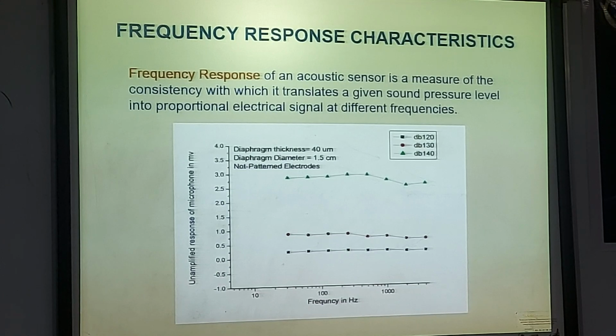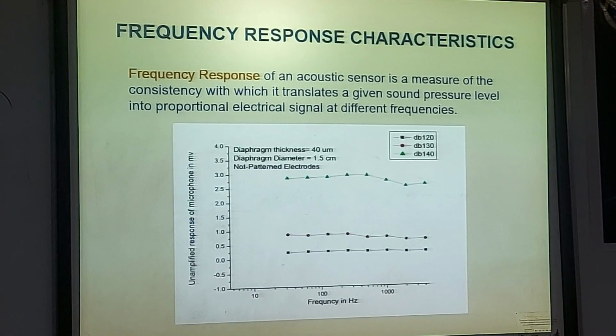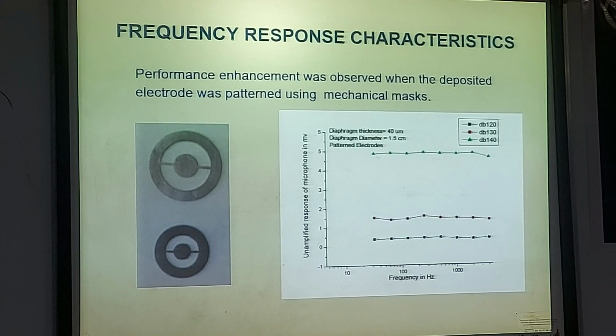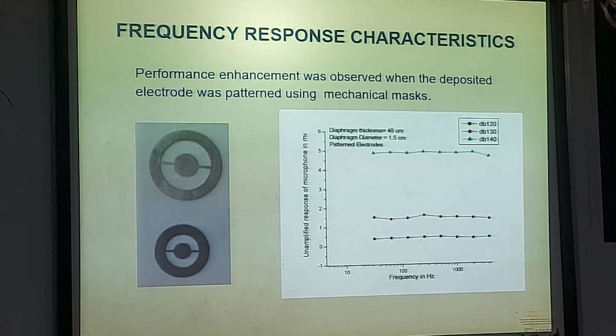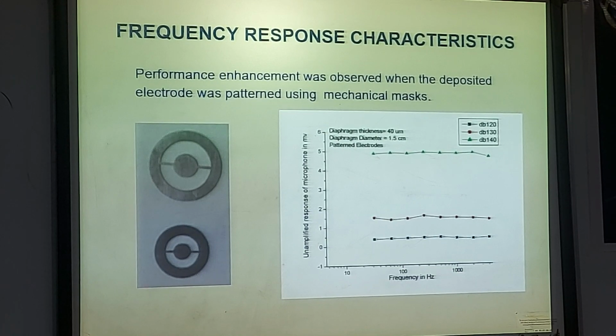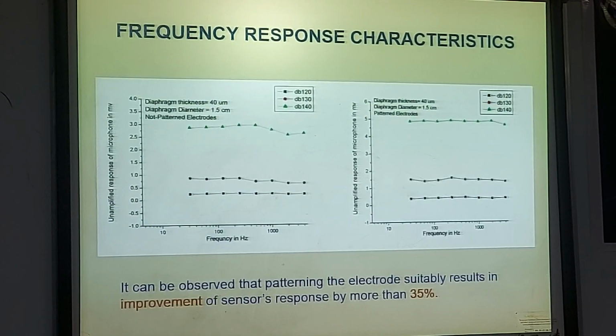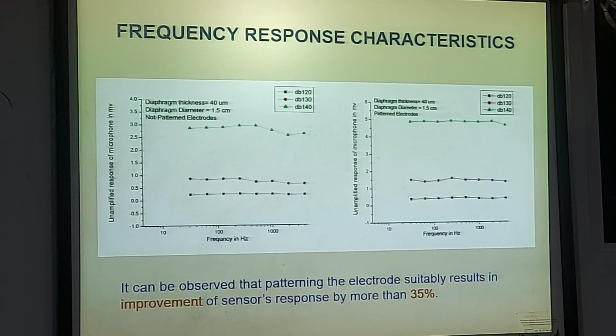120 dB, which is shown in the dark color, other one 130 and 140. So you can see that the response is almost flat, uniform. And then we also did this with a segmented electrode arrangement, and we got an enhancement of signal of about 30%. So this is a comparison of the same. I will not go into the detail. What we found was that patterning the electrode suitably results in improvement of sensor response by about 35%.